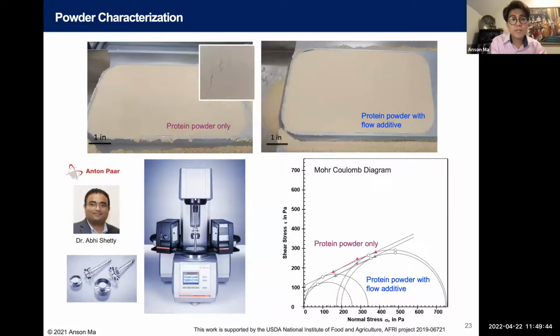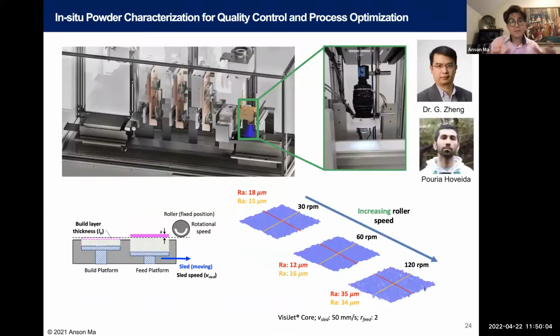And then we also did some collaborative work with Anton Paar. They have a shear cell that you can use to look at powder rheology. By looking at two samples, one with the additive, you can correlate the intercept in the Mohr-Coulomb diagram back to how flowable the powder is and how nice the spread layer is. So that could be a good tool.